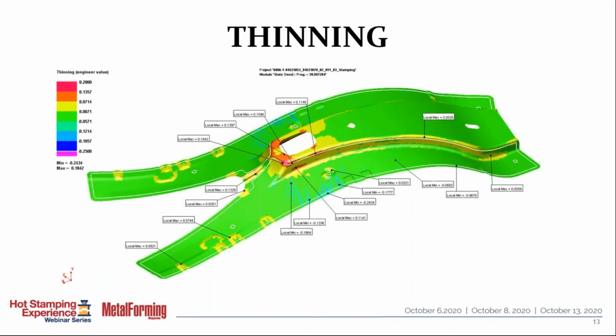Generally, the industry is working between 17 and 20% thinning as a maximum allowable thinning. In this case, you can see the outlines of the finished parts, and those are generally outside of the area where we're getting some thinning, which isn't too much, but it's still getting up into that 15% range. But that was considered acceptable, and so we were able to proceed with the project based upon those results. And we did find that we did not have any split issues in this area when we built the tool and went into production.